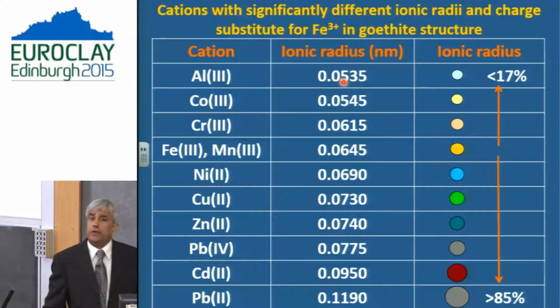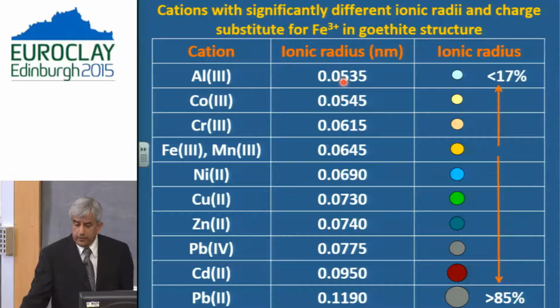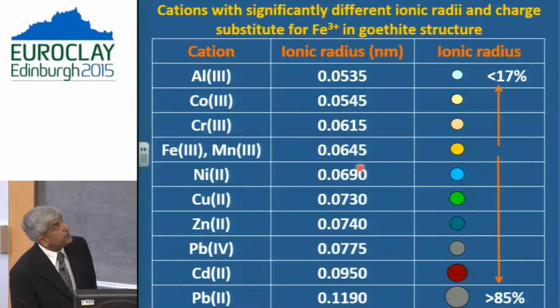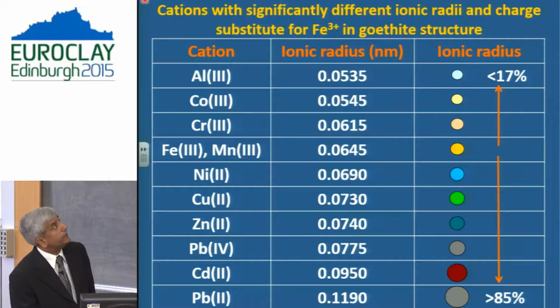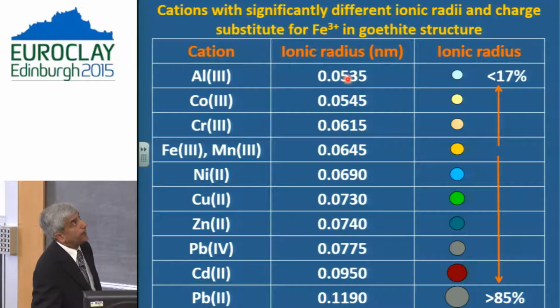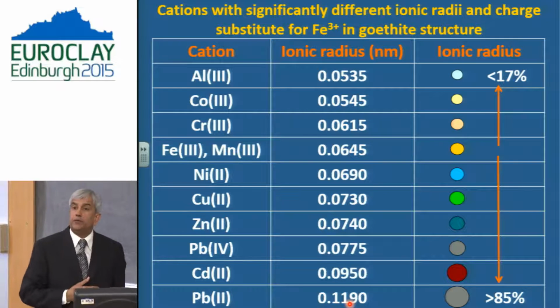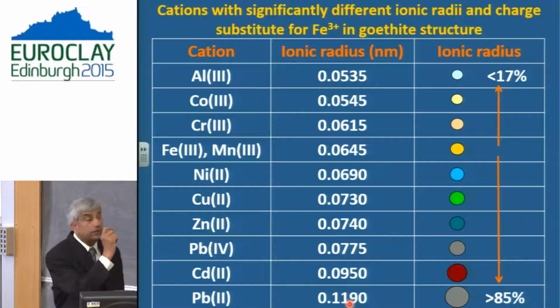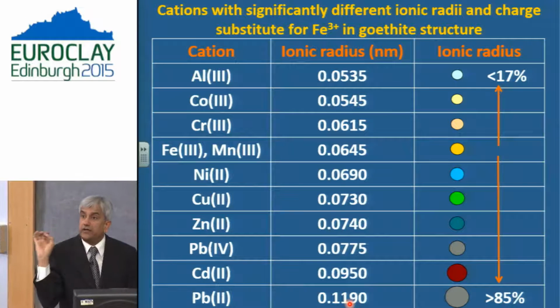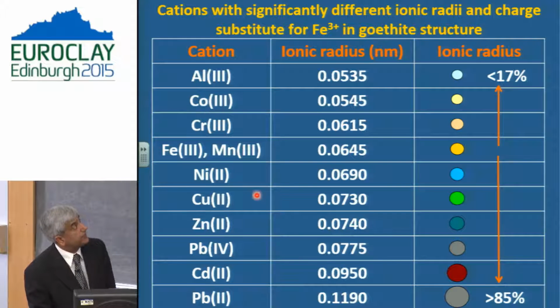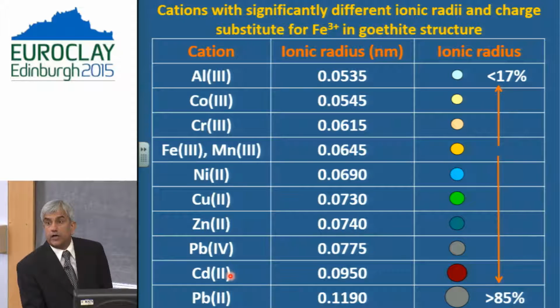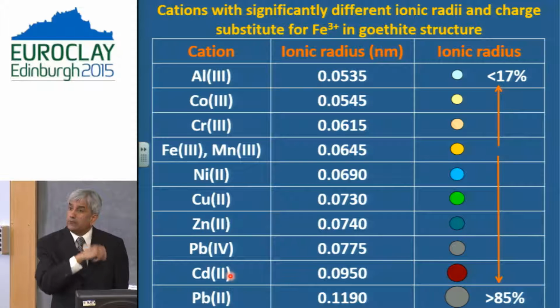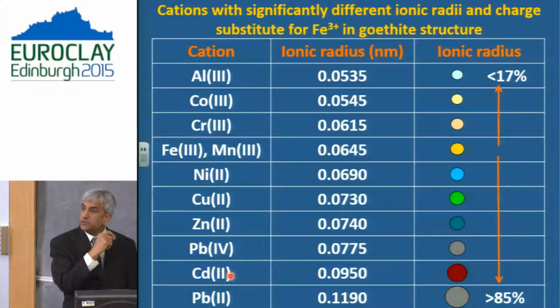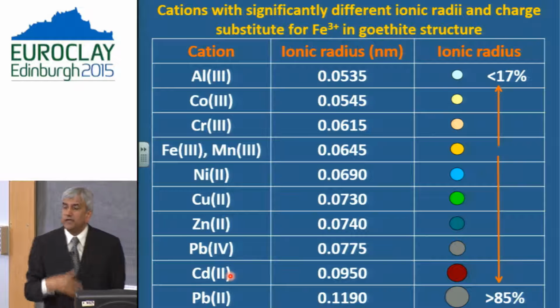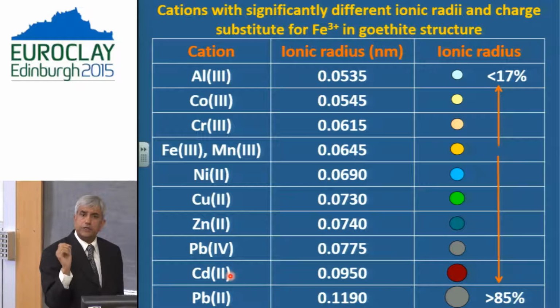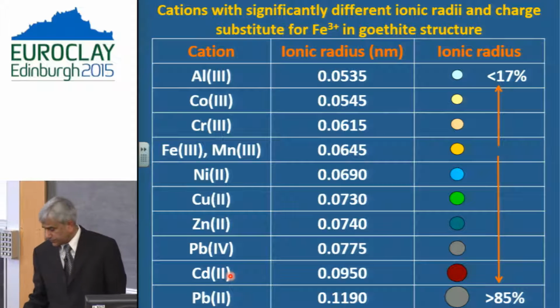When you look at the list of elements which substitute for iron, you see the size is highly variable, almost varying by a factor of 2, starting with aluminium, which is about 0.05 nanometer, and going to lead, which is nearly 0.12 nanometer. So there are highly different cationic sizes and different charges. They vary anywhere from +2 to +4 charge. So a lot of these elements which have very different size and different charge can substitute in the structure of iron oxides, and obviously it has consequences in terms of reactivity or the product which will be formed under those systems.